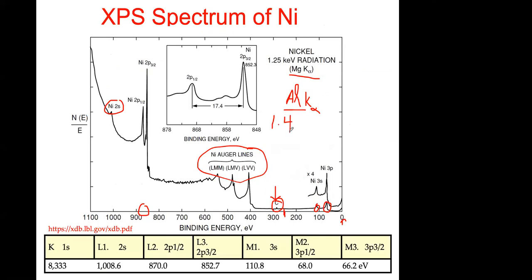This is 1.4 kilo electron volts, so it's about 200 electron volts higher. That means the kinetic energy of these Auger lines is not going to change, but you make the analysis with this energy. The kinetic energy of these electrons is the same whether you use magnesium or aluminum. But when the XPS instrument does the calculation, will it appear to have a higher binding energy or a lower binding energy?